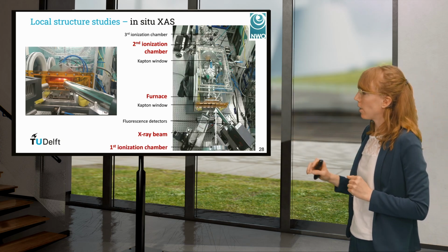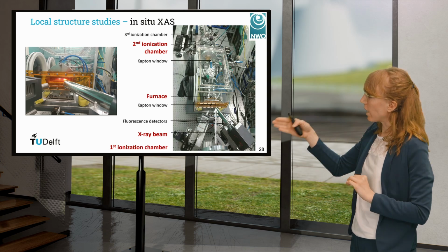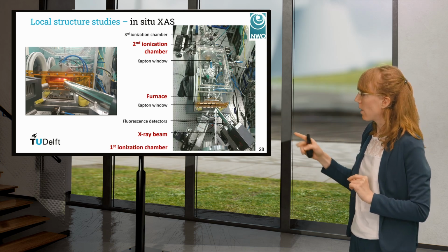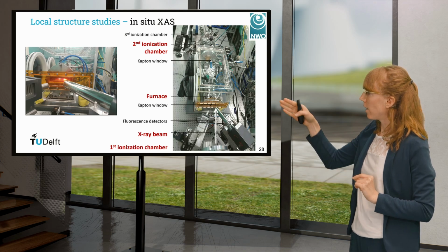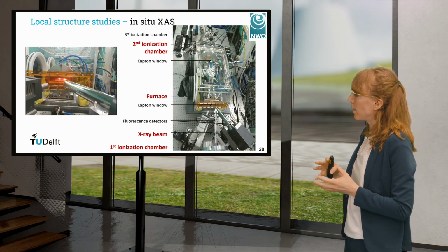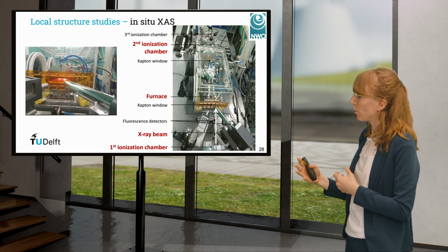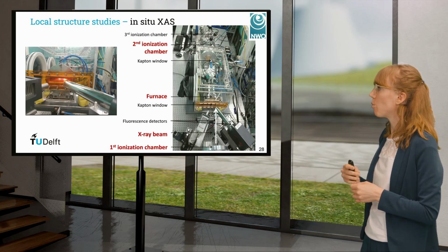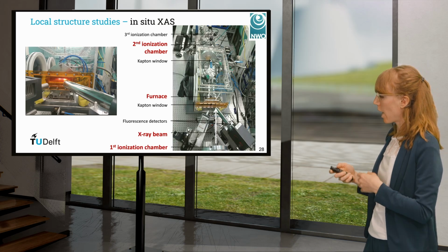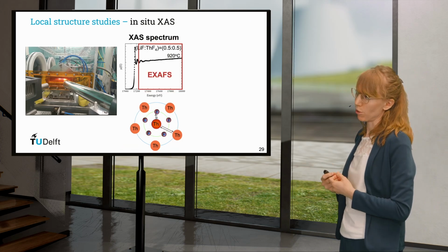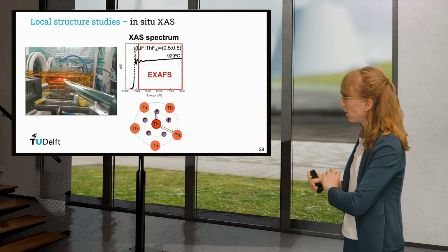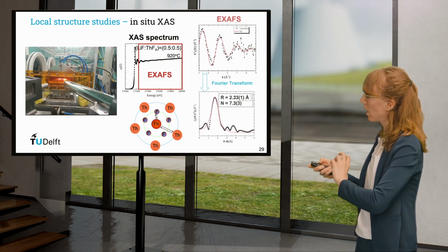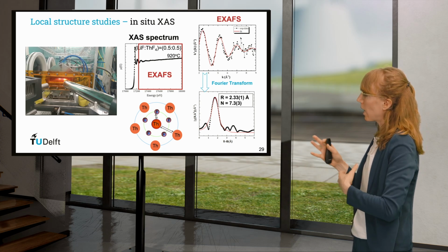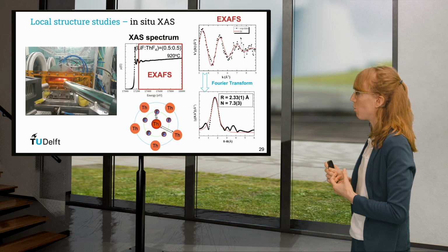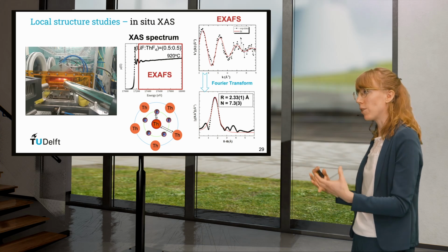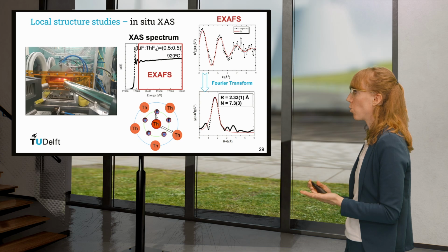You can see on the picture how everything is set up. The X-rays come from the bottom of the picture. They go through the measurement cell and come out. The X-ray intensity is then measured before the sample in the first ionization chamber and after the sample in the second ionization chamber. And with that, we can get the absorption coefficient. I'm going to concentrate on the EXAFS region as I mentioned. After some mathematical treatment and some Fourier transform, we get the figures on the right, which we can fit. And when we do this fitting, we get information on the local structure.